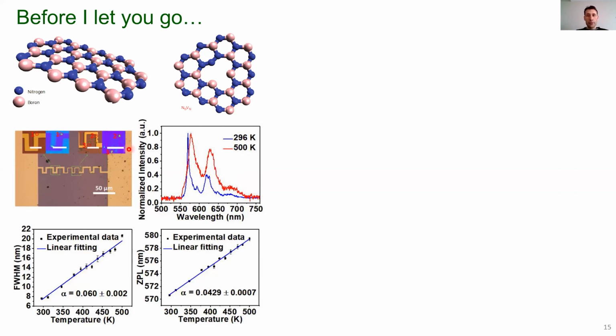And recently we used this to measure what was the temperature of this electronic circuit. It's quite hard in this picture to see, but there are a few bands here in this electronic circuit, and there are different thicknesses, which means the Joule effect is going to be different for the different areas. And we positioned, by using a transfer method, small flakes of hBN onto these positions, and we were able to monitor the temperature in 3 different positions.